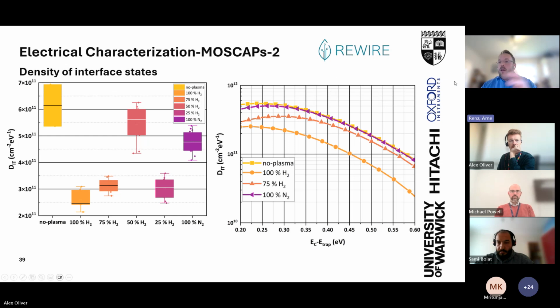And by applying our processes, by switching over from thermal oxidation to an ALD-based process, that gives you the flexibility also of preparing your samples in the ALD chamber before you put down the oxide. It also gives you the opportunity to anneal the oxide after you've done the oxidation. So you basically have more degrees of freedom, more degrees of control, as Michael rightly pointed out before. But we have managed to get a process that was very competitive. It's basically state of the art, and even exceeding that, with a low density of interface traps.